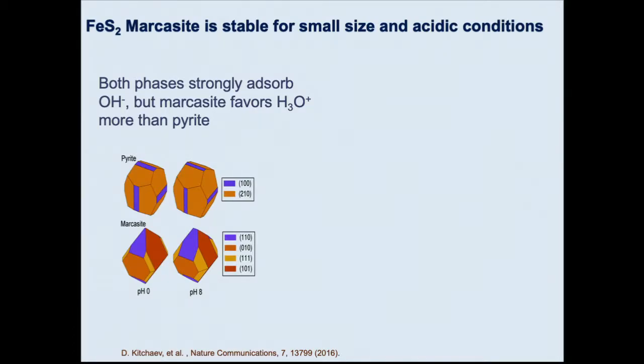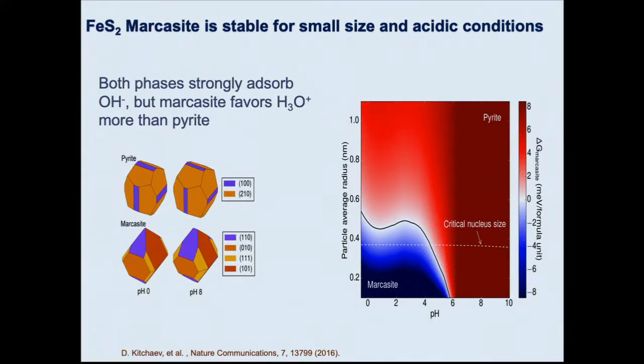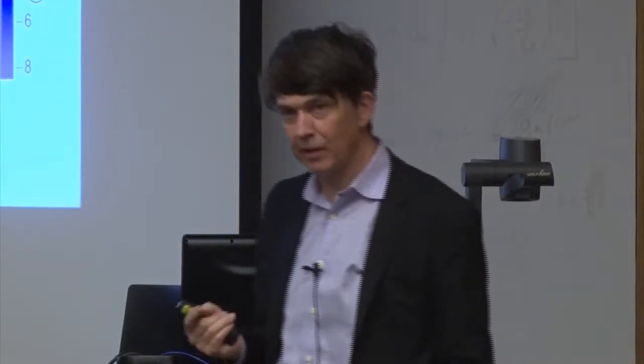And when you actually do that, you can make a phase diagram as a function of pH and particle size, right? So here you're really small, here you're 1 nanometer, so huge. Here's the pH, and what you see indeed, marcasite is the stable phase at low pH, so in acidic environment, and at small particle size. And that is actually because marcasite has an easier time doing adsorption of H3O, so actually protons combined with water. It has a stronger adsorption energy of that. So this is very consistent with what people find in nature.